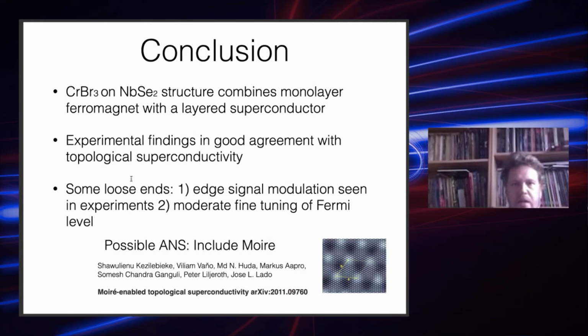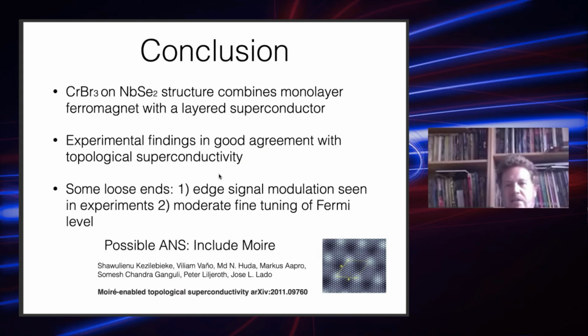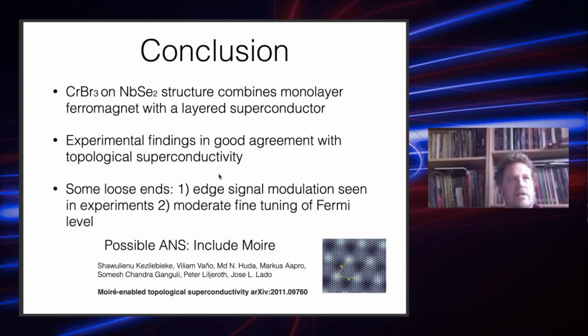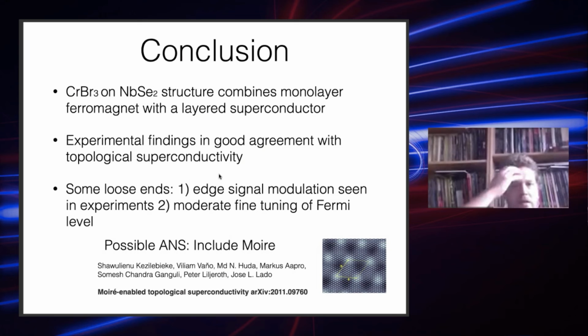Okay, so here's my conclusion. The chromium tribromide, niobium diselenide, 2H niobium diselenide structure combines a monolayer ferromagnet with a layered superconductor, and the experimental findings in these systems are in very good agreement with topological superconductivity. And of course, as a community in the last 5 to 10 years, I think we have learned some humility in our declarations of topological superconductivity, especially considering the rocky road in the nanowire experiment. So it's better to be a little bit reserved, even though there seems to be a pretty good match.